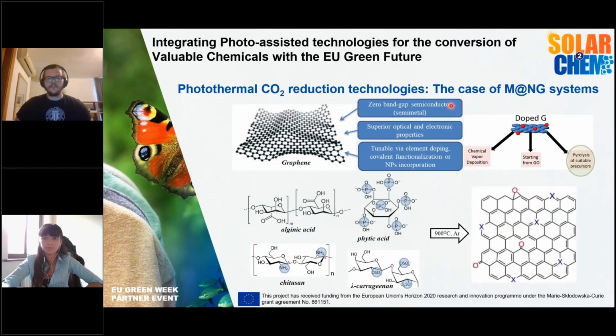Regarding our choice of material, we are synthesizing graphene or graphite carbon scaffolds from natural polysaccharides or from natural acids. This is very convenient since by choosing different precursors, we can obtain different heteroatom dopings, or by combining different polysaccharides in the synthetic procedure, we can obtain several heteroatom dopings on the same scaffold. So it's both cheap and very simple synthetically.